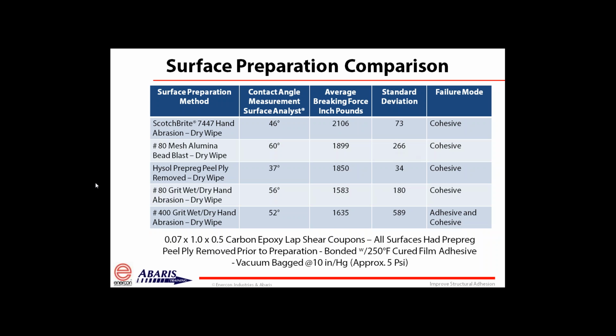So when we look at the overall ability to get good numbers, the Scotch-Brite post peel ply seems to give us the best numbers, and with a very medium standard deviation. Now, I will tell you that this is one operator doing all of the coupons. If I were to take 10 different operators and do all of these coupons with those same 10 operators, I would have widely different values, except with the pre-preg peel ply. That is going to stay very consistent, and for that reason we recommend looking at designing around numbers that are consistent and have a very consistent surface effect.